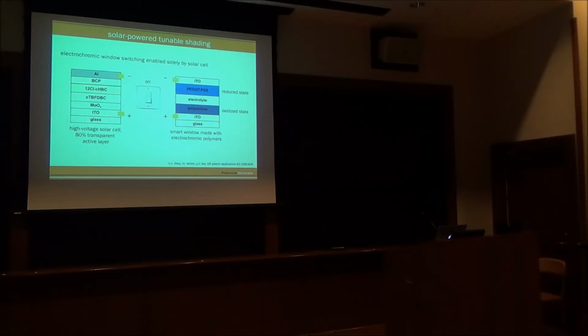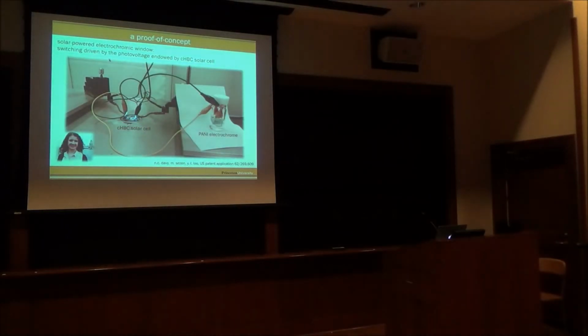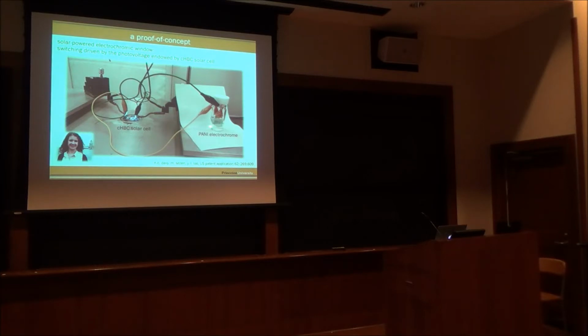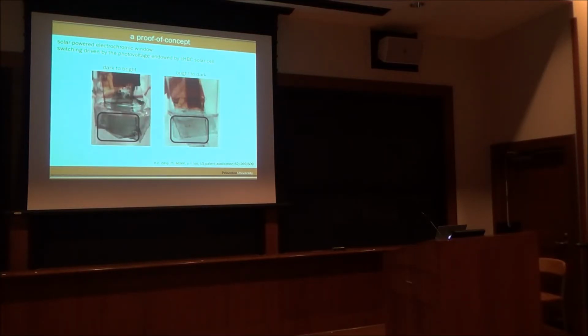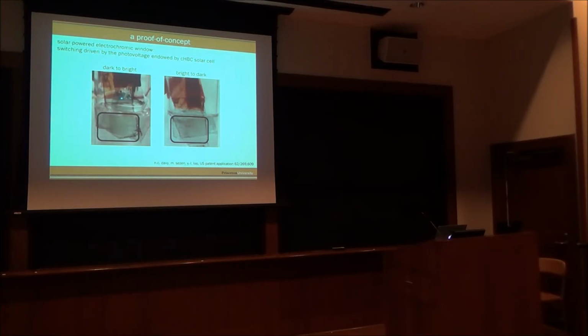So the idea is then to hook them together. So this is Melda Seson's work. That's the polyaniline. The liquid is the electrolyte. This is our very first demonstration, and you can see the solar cell that's here that's powering the switching of this electrochromic film. So this is as we go from dark to transparent with the solar cell turned on, or with the light turned on to illuminate the solar cell. And then this is as we go from bright to dark. Again, this is with a liquid electrolyte, and the counter electrode here is indium tin oxide. So this is only half a window, if you will.